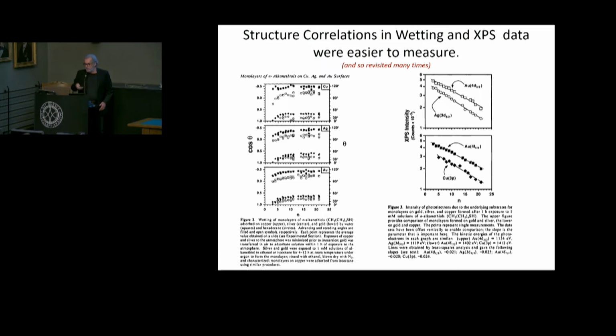And you see behaviors like for different metal substrates, gold, silver, copper, that as a function of the chain length of an N-alkane thiol, the contact angles with water and hexadecane approach very hydrophobic and very oleophobic limits very rapidly. And what you're seeing is that the underlying substrate is being shielded from the contacting fluid by the presence of this molecule.